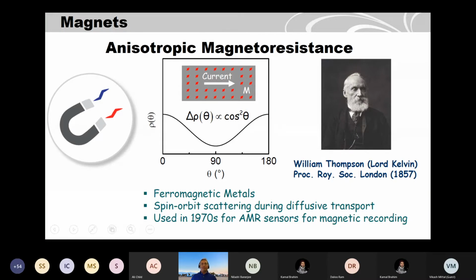several tens of years ago. Then in the 1970s, what people actually used for magnetic data storage, and already from that time, spintronics was there. For example, spin orbit scattering actually helps to make an anisotropic magnetoresistance device. If you have only a ferromagnet and you apply current, the current has different resistance depending on the orientation of the magnetization. So this is the resistance change with angle, what you see.